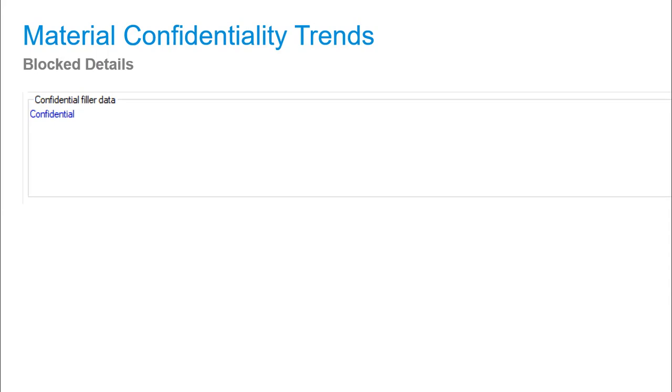So a lot of times, to protect the data, especially for those that have a lot of proprietary work, some people compound their own material and put their special spin, or, like Brian likes to call it, foo-foo dust into it, whether that's a fiber, a stabilizer, or an additive. Sometimes a mineral of some sort for stabilization of heat or warp, stabilized shrinkage. And it's left out of the mechanical aspect. And that's a danger. We need to have the mechanical data of all these components in order to have the proper micromechanics for accurate warpage predictions. So that's one thing we need to be cautious of when we see confidential data and we have no way of knowing what that is.